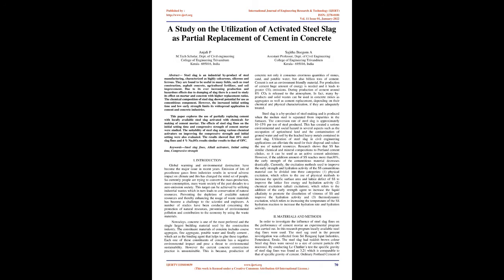This paper explores the use of partially replacing cement with locally available steel slag activated with chemicals for making of cement mortar. The effects of steel slag fines on the initial setting time and compressive strength of cement mortar were studied. The suitability of steel slag using various chemical activators on improving the compressive strength and initial setting were also evaluated. The results showed that 18% steel slag fines and 4% Na2SO4 give results similar to that of OPC. Keywords: steel slag fines, alkali activators, initial setting time, compressive strength.